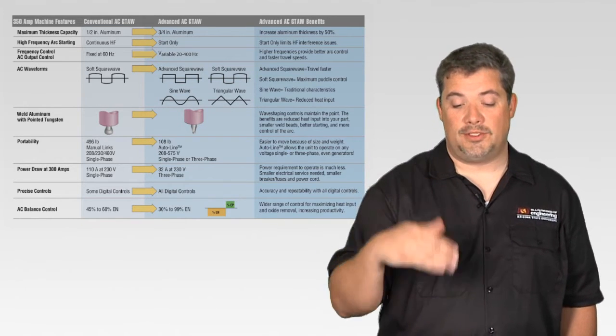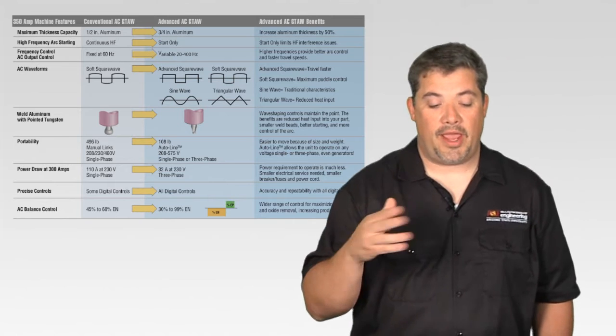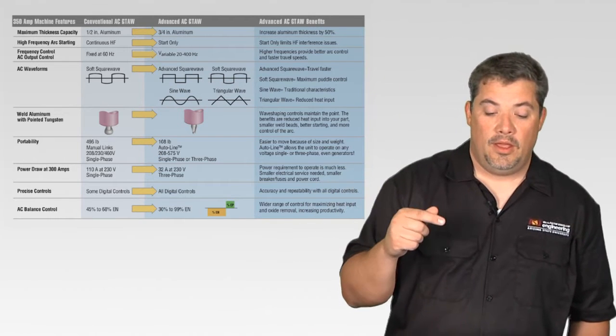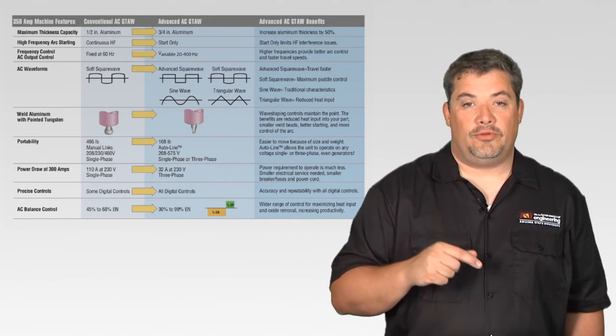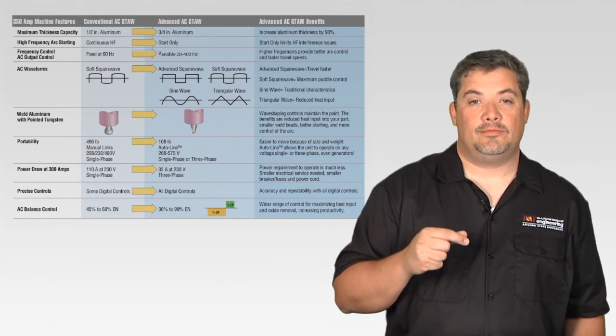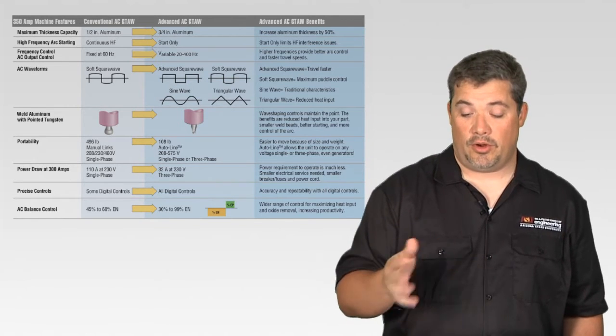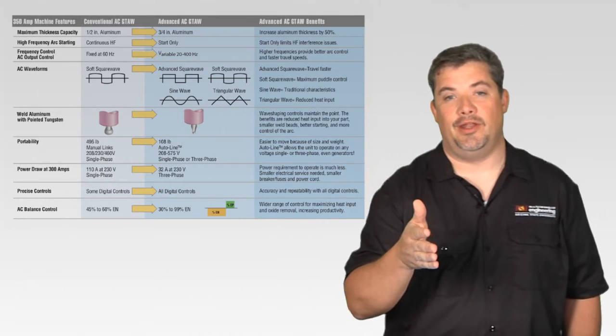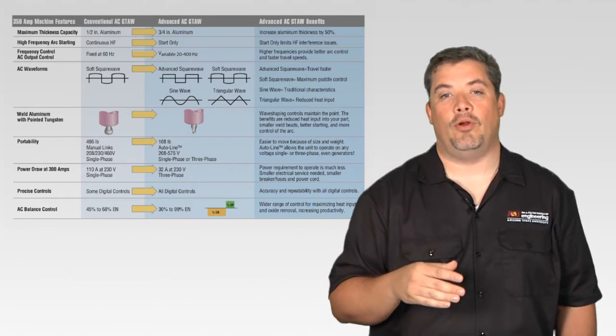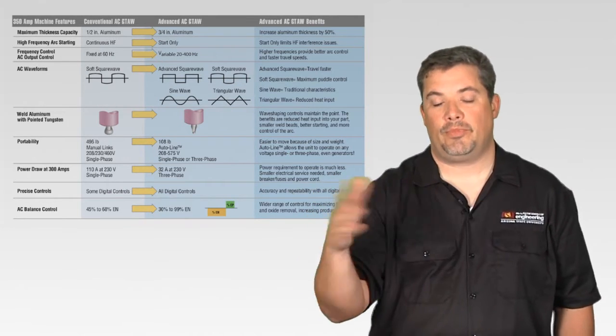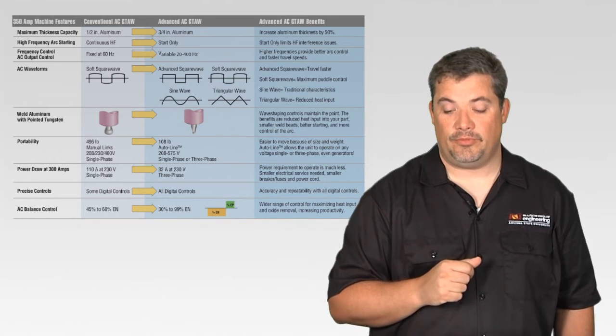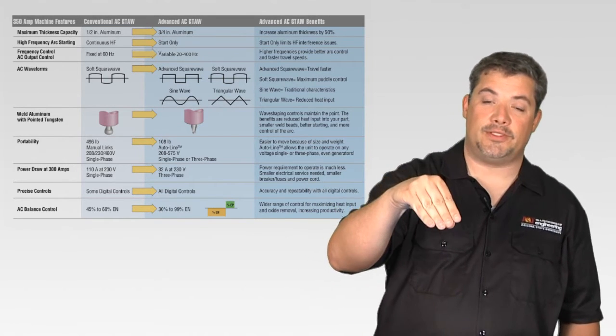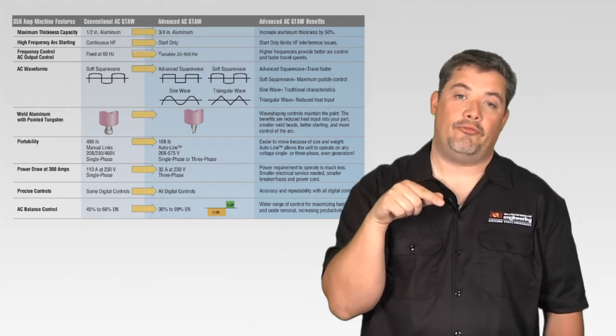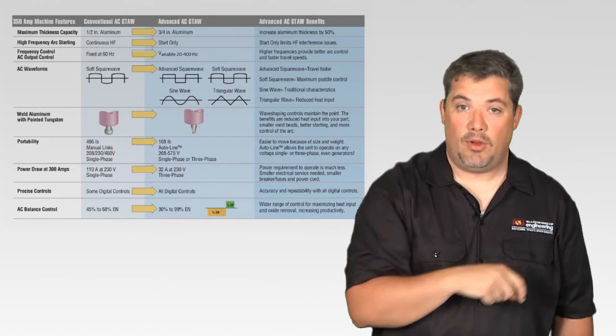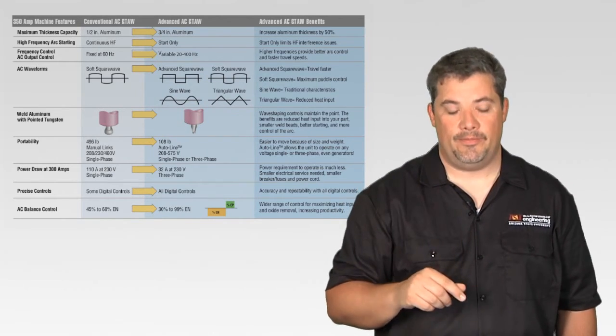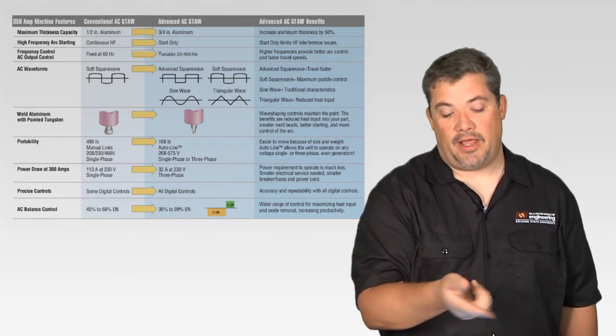Or again, we're drastically reducing the use of it by having it only on the start of the arc. We have our output control from being fixed at 60 hertz. Now we have variable from 20 to 400 hertz depending on the machine. Some machines are limited at 250, others go up to 400. But 20 is the bottom, 400 is the top of the range typically available. It lets me focus that arc, punch it into the corner on a fillet weld, or make a smaller weld, whatever I might need.